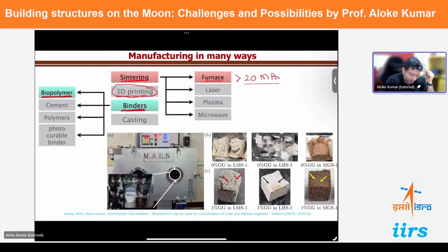But then we made something called MARS. MARS stands for Martian Atmosphere Simulator. Here we make it vacuum, just like the Martian vacuum. Mars has, I can't recollect it off the top of my head, about 100 times thinner or less pressure on its surface than Earth, 100 or more, something like that. So we create this vacuum, Martian-like atmosphere, fully carbon dioxide, and we make our bricks in these small jars here. We have made bricks with different types of materials, including now Martian soil also. And we have seen that with biopolymers, they can be used for lunar and Martian regoliths and made into bricks. It is now available on bioRxiv, which is a preprint service. If you want, you can read the entire paper. We have been able to make really, really strong bricks with that, stronger than 20 megapascals.